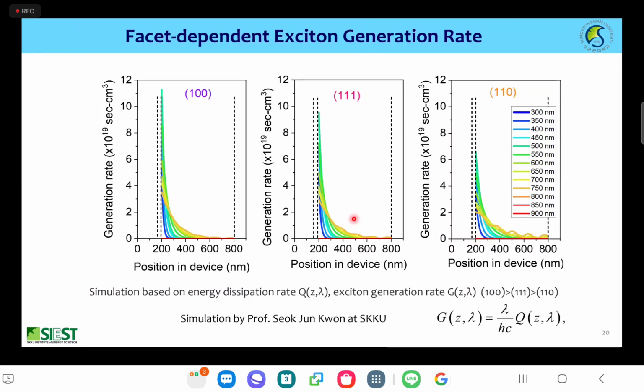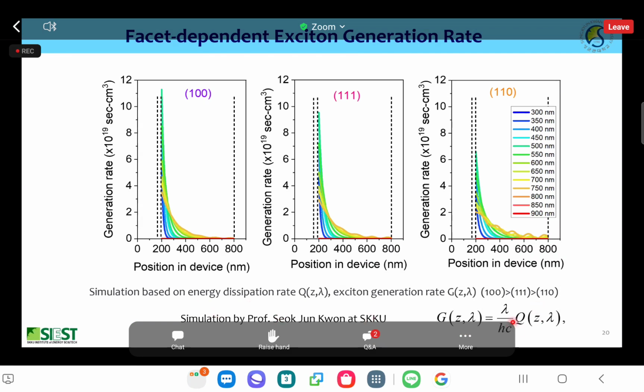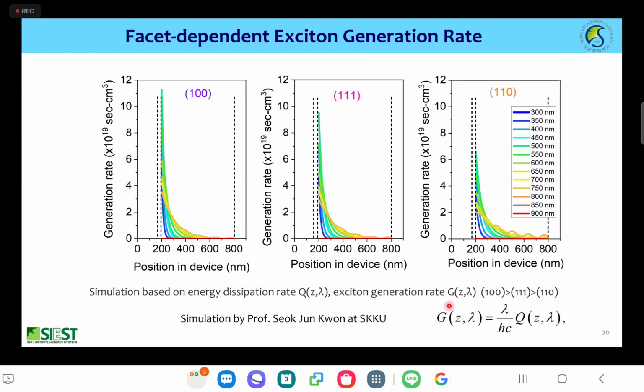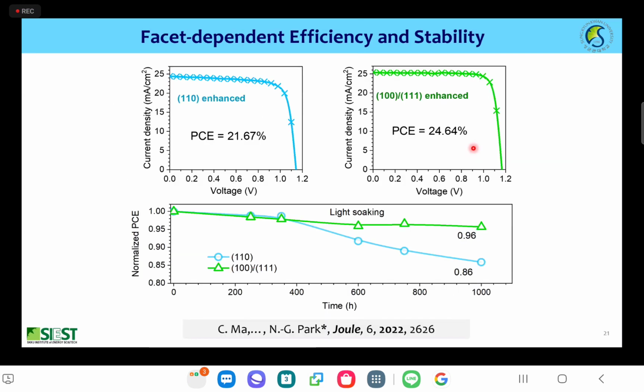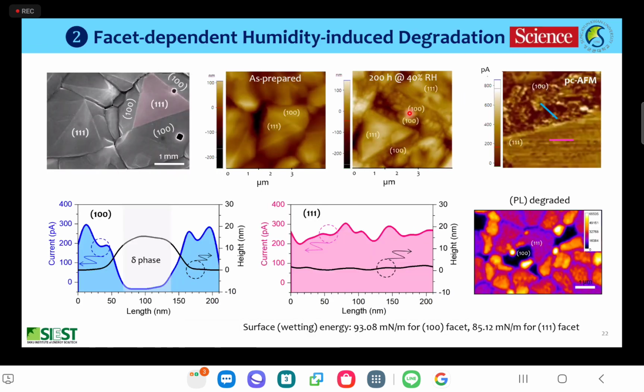Why do the 100 and 111 crystal facets show high photocurrent? Based upon the energy dissipation rate, we calculated the exciton generation rate, and we found that the exciton generation rate is much larger for the 100 crystal facet than the 111 crystal facet. Eventually we observed higher efficiency from the 100, 111 enhanced crystal facet films. We also prepared a 110 enhanced crystal facet film, which shows much lower conversion efficiency, as I mentioned earlier. In addition, we also found that the light soaking stability is improved with these specific crystal facets.